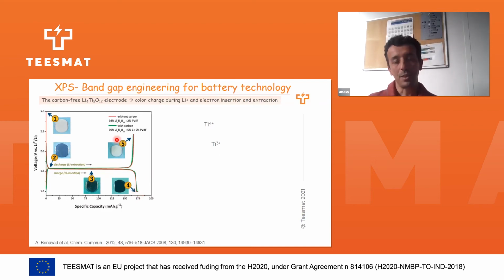Usually for these materials, we have to use a binder with black carbon to make it conductive. But in this case study, we did some surface treatment to these materials, so we do not need any more carbon to cycle them. And it's interesting here, as you know, LTO has a white color. That is our pristine electrode. When we cycle, the color changes to blue and at the end of discharge becomes black. When we charge, we get back our original color. That means we have a redox process. We move from a semiconductor material to a metallic-based material. That's why it becomes black, and it's quite reversible. So we don't need any black carbon to help this material work, just surface engineering.